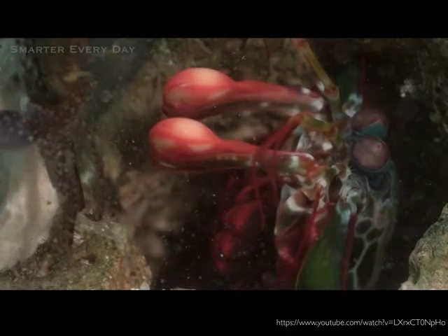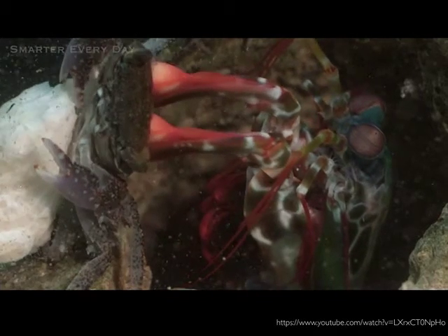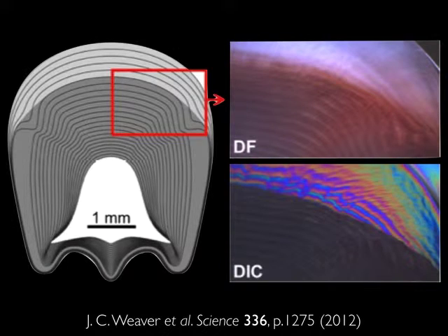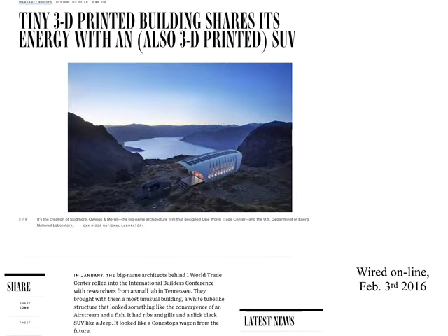David Kisailus and co-workers, a few years ago, asked exactly this question, and so they investigated these clubs with a number of techniques. And they found that it's due to, again, the helical arrangement of chitin, but with an incredibly well organized helix with a graded pitch that really dissipates the force and prevents crack formation. It's really quite spectacular. So this example from nature can be a good inspiration also for artificial materials, because maybe you have heard that 3D printing is now going beyond the lab and really being seriously considered for manufacturing large-scale structures like even houses and cars and bridges.